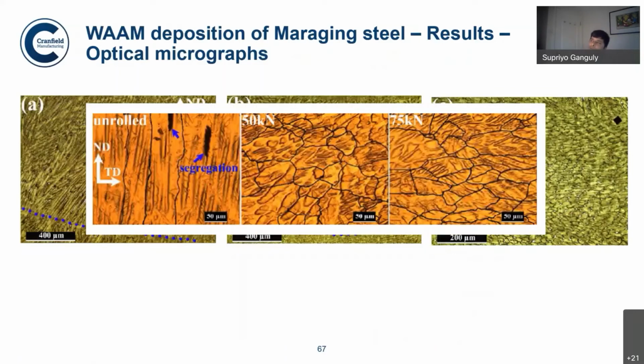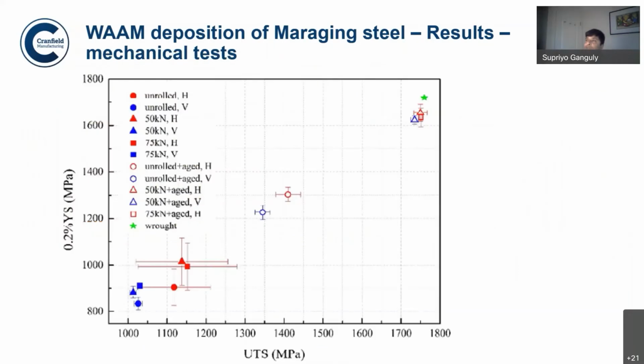So the unrolled one has completely elongated grains, as you have seen in case of titanium and all, while the rolled one has now started to show the high angle grain boundaries that we like to see in these deposits after rolling. How it is important will be shown in the next slide: this rolling then allows the material to age properly. And why? Because it allows it to solutionize properly.